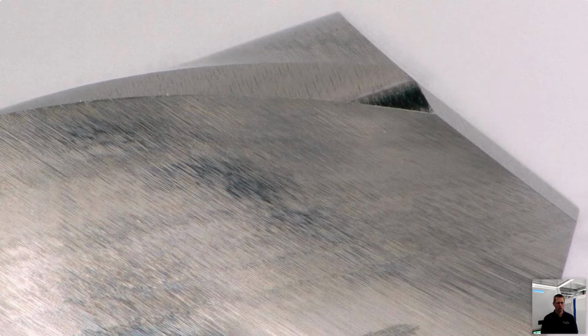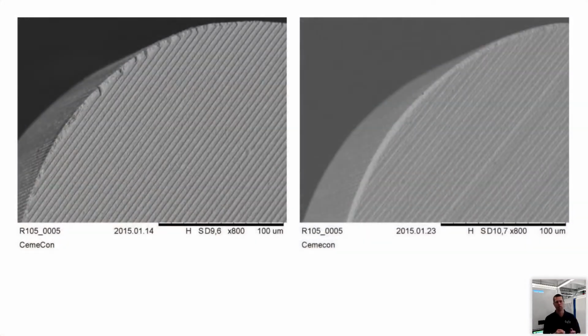This is a technology which we normally use for carbide cutters to support the cleaning and to make the cutting edges more homogeneous. That's what you're seeing here, this nice animation of round, the typical end-mill style inserts. On the left-hand side, a perfectly ground and honed insert, but still you have some marks, some scratches in the cutting edge. And on the right-hand side, you see after wet blasting, the cutting edge is by far more homogeneous.